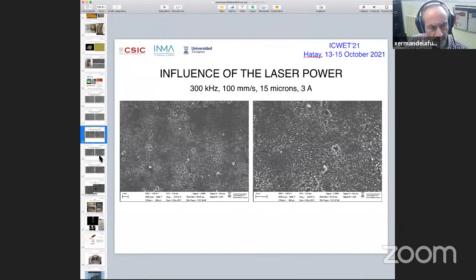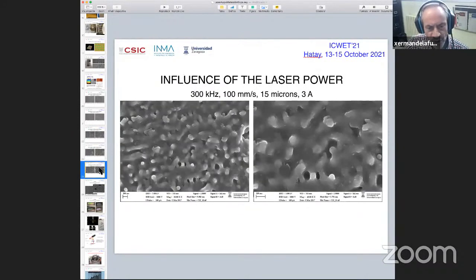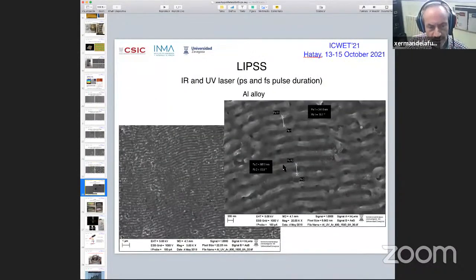And you can see that this is with lower power. As you increase the laser power, you change their morphology. And this is a very well-known effect. But if you do it at the right intensity of the laser and other conditions, then you can get a very well-ordered array, as you see here, which maybe if you use a UV laser will go below the wavelength of visible light. In this case they're just above 100, 200 nanometers in periodicity.